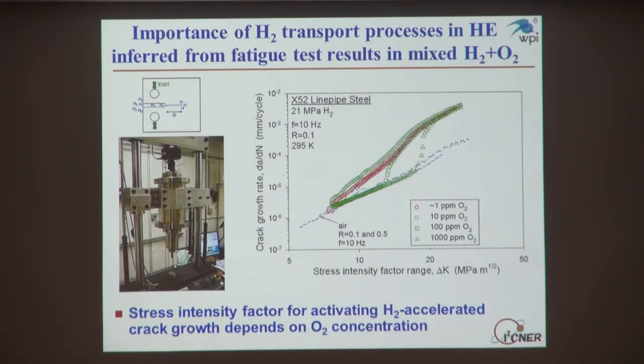And this is important from a technological perspective because these environments may not be pure hydrogen. And what we find is that as the concentration of oxygen increases, the stress level for activating these hydrogen accelerated crack growths increases. These results seem to infer what I mentioned earlier, that the transport processes are important. So the role of oxygen here is not that oxygen is diffusing into the metal and somehow interfering with how hydrogen interacts with the metal. There's something about the way that oxygen interferes with the hydrogen transport processes.